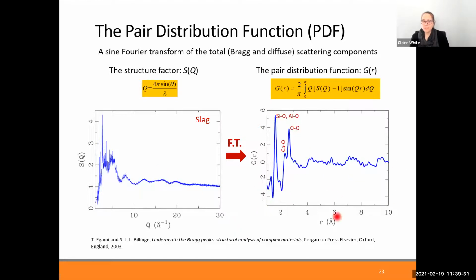Us humans, we tend to be able to interpret real space better rather than thinking about, okay, what is the local structure of this slag in reciprocal space? It's very hard to understand. If you look in real space, then you're looking at bond lengths in the nearest neighbors, and then you're looking at atom-atom distances the further you go out. So this is a histogram of all atom-atom distances in your material.